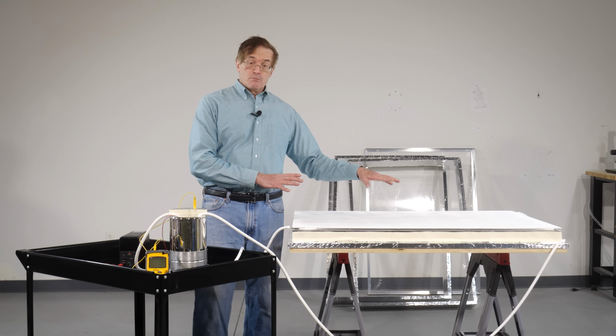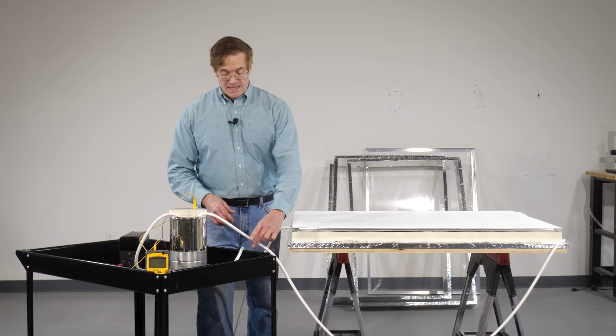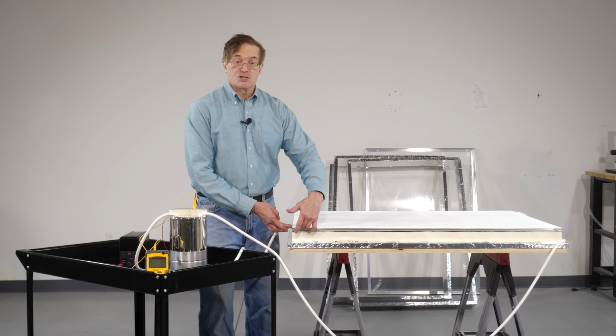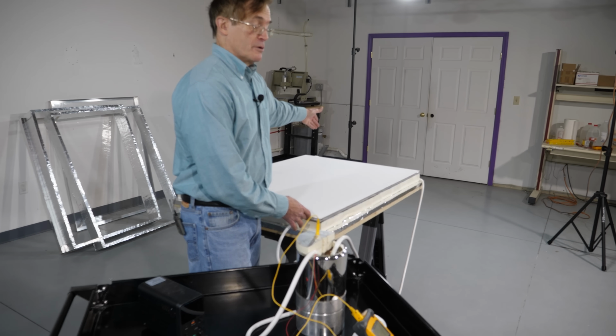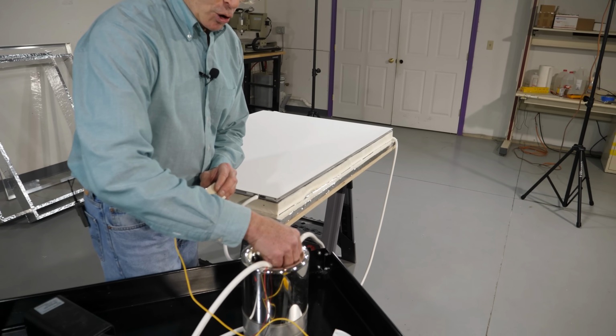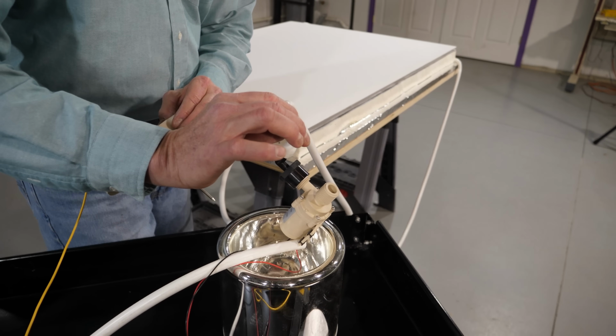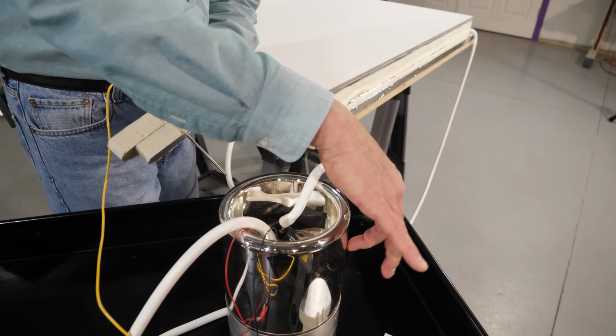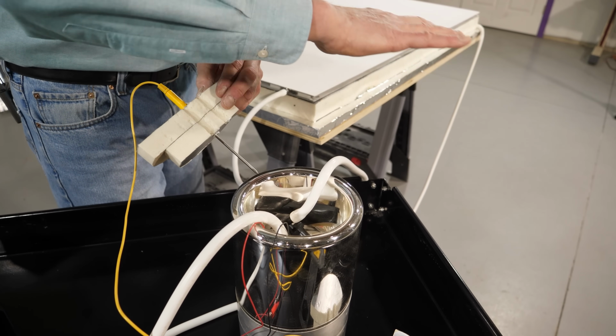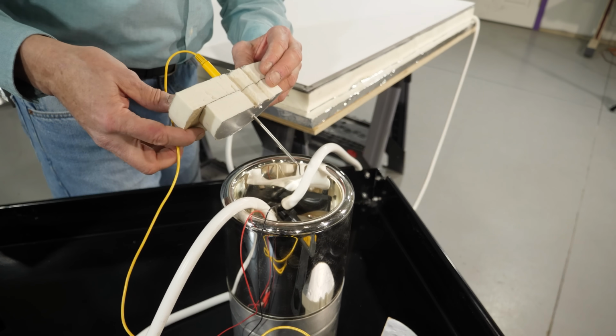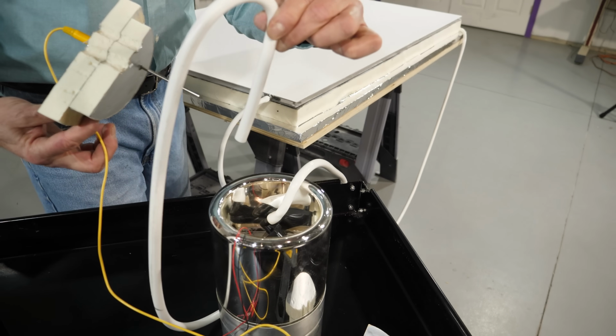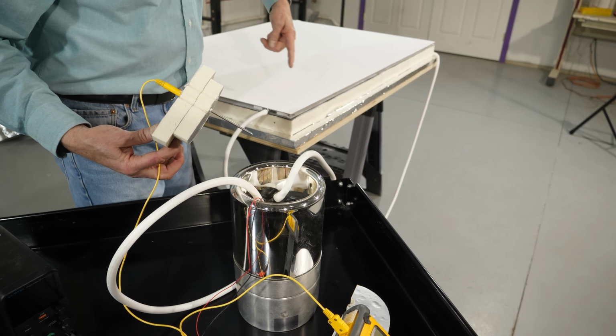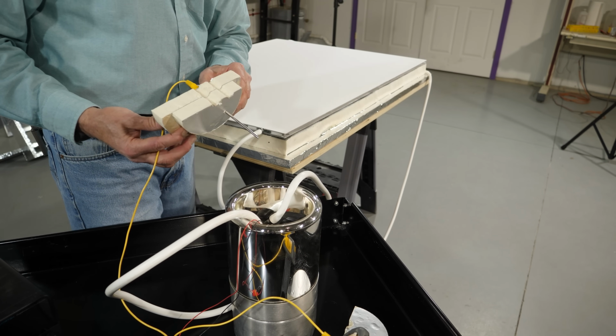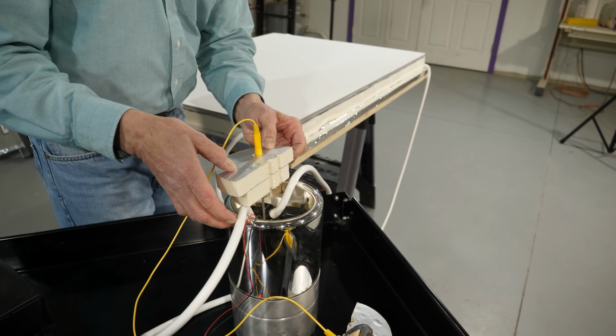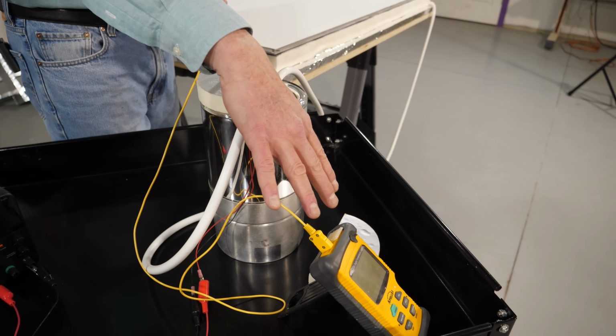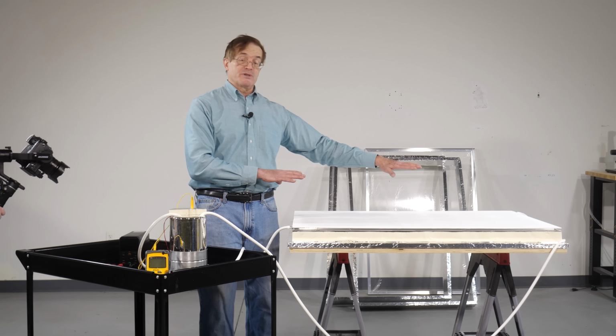Now, to demonstrate that this process actually does work, what we did is I hooked two rubber tubes up to the heat exchanger on the two ports that are located at opposite corners. One side goes to a submersible pump that's immersed inside of a vacuum dewar that effectively blocks all thermal transfer between the outside environment and the inside, which is going to be filled with water, which will circulate in a loop between and back to the reservoir. Inside of the reservoir, I have a thermocouple, a temperature gauge, and this is going to read the temperature over here, and we're going to watch the temperature change as we put this out under the sky.